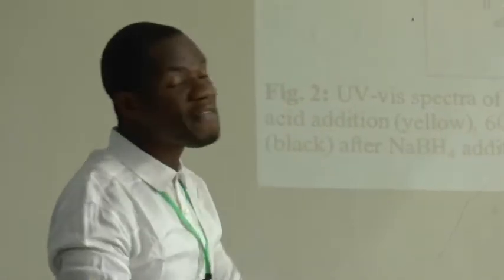Then the third and fourth samples were taken 5 minutes and 10 minutes after the addition of the strong reducing agent sodium borohydride. Now from the graph, we will see that plasmonic absorbance only appears around 562 nanometers, 5 minutes and 10 minutes after the addition of the strong reducing agent, indicating the formation of small clusters of copper nanoparticles.